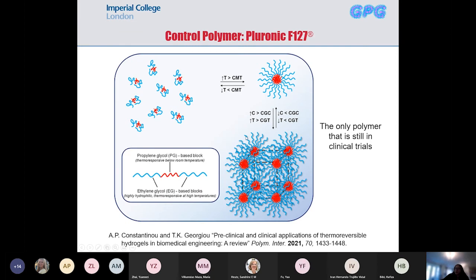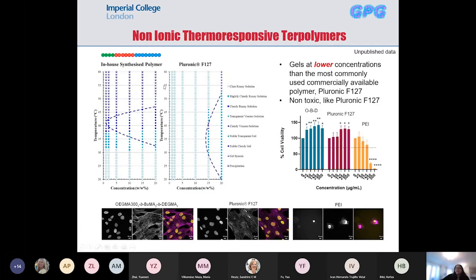It is well established that the way they self-assemble is they form micelles, and then they come together, with spherical micelles forming a cubic structure, and that's the structure you have within the thermogel. Now, if we look at the phase diagram of the Pluronic, it doesn't gel in similar ways to our polymer. This is our polymer on the left, and the Pluronic is on the right. You can see that the Pluronic is almost a gel at room temperature, and indeed is a gel at room temperature at very high concentrations. But it does require much higher concentrations than our polymer in order to gel.